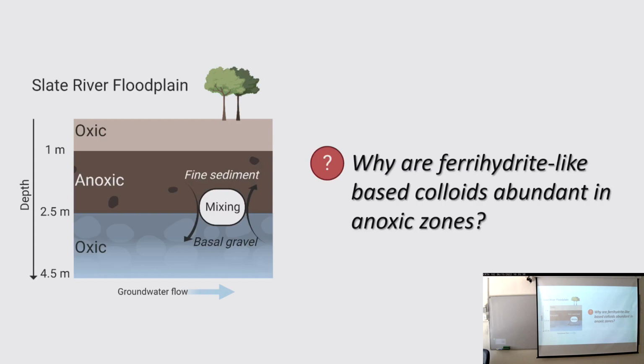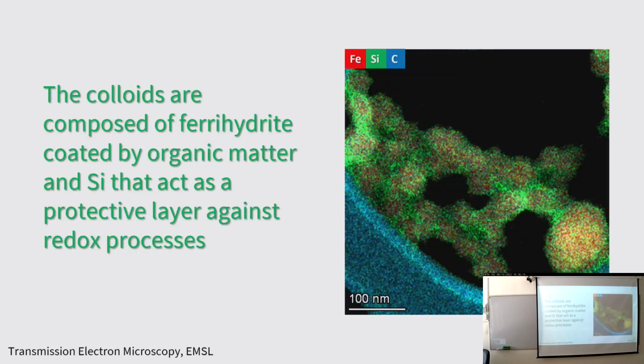But I want to stop and recollect for a second that we initially detected these colloids because of high levels of iron 2, of ferrous iron. But I've just shown you that we have a high contribution of ferrihydrite, so iron 3. And that raises the question, why do we have oxidized ferrihydrite-like colloids that are abundant in anoxic reducing conditions? It appears, especially from the literature, that coatings of organic matter and silicon can actually protect iron minerals from redox processes. And if you look at the overlap of iron, silicon and carbon, it does really seem that the carbon or the organic matter and the silicon is coating the iron. So it's coating the ferrihydrite, serving as a protective layer against redox processes.